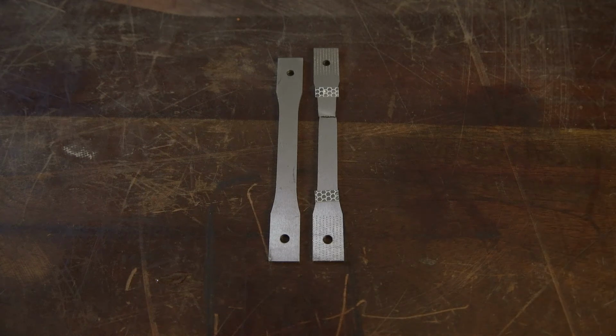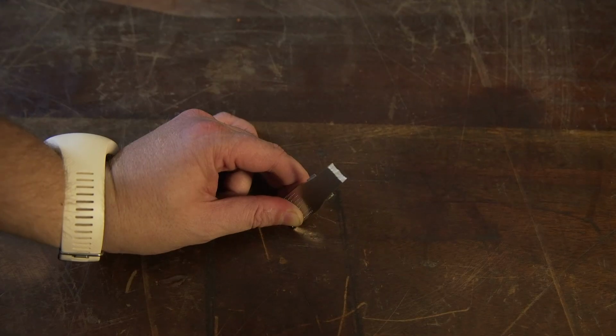So here we have our failed T6 sample compared to an unbroken T6 sample. As you can see, the failed sample has plastically stretched an amount. When we examine the fracture surface of the T6 specimen, we can see that it is very flat with very little plastic deformation, and this is indicative that the T6 failed in a brittle manner.